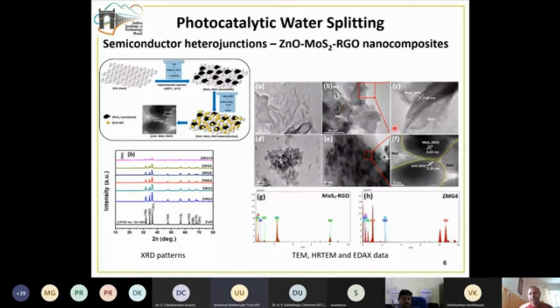And this is the HRTEM image, which is the high resolution transmission electron microscope, which shows the lattice fringes, which could be seen here. And these are the nanospheres of zinc oxide, which is the pure zinc oxide here. And this is for the nanocomposite. So you can see the big sheet type of thing, on which there are certain regions with this black colored MoS2, and certain other places where you can also see the zinc oxide lying on that.